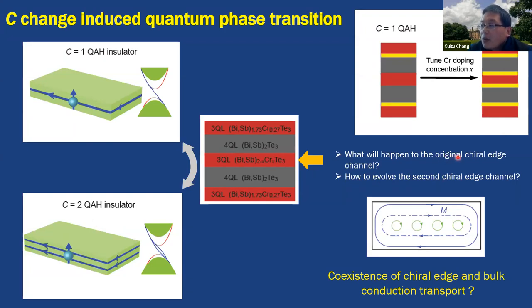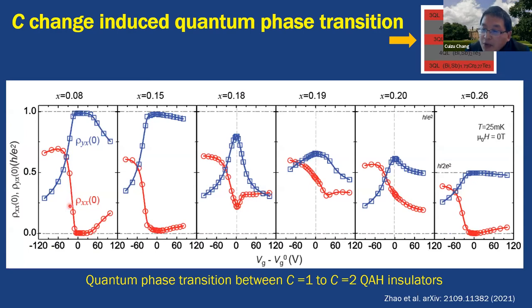What will happen to the original chiral edge state from the C equals 1 quantum anomalous Hall, and how does the second chiral edge channel evolve in the C equals 2 quantum anomalous Hall insulator layers? And here are the transport results. We can see that with a very low doping level of 0.08, it indeed shows the C equals 1 quantum anomalous Hall state. With increasing chromium doping level, we can see the Hall resistance monotonically decrease, and the longitudinal resistance first increase and then decrease.